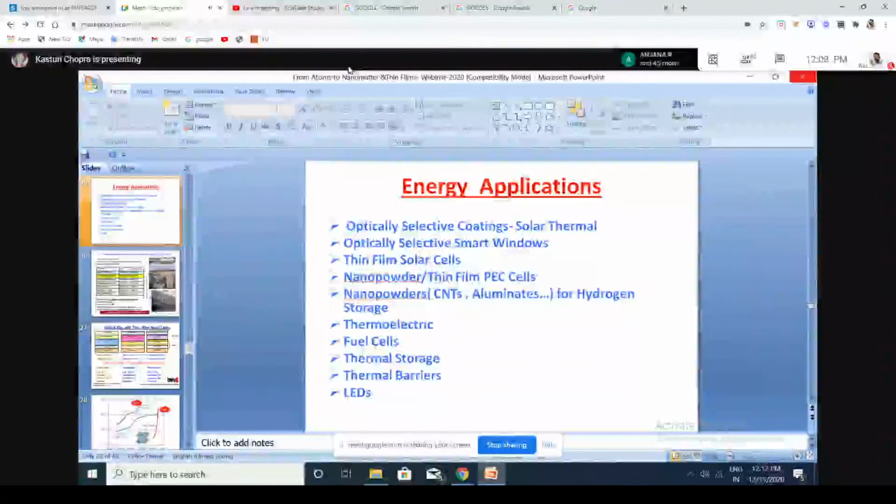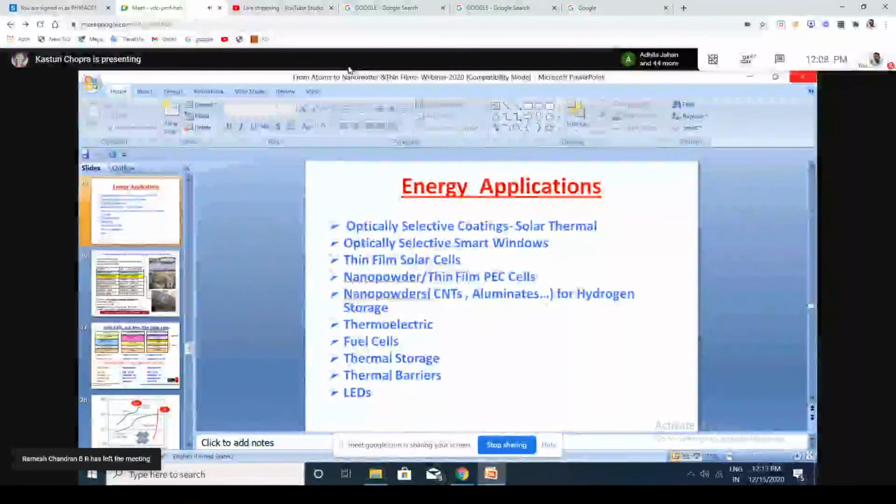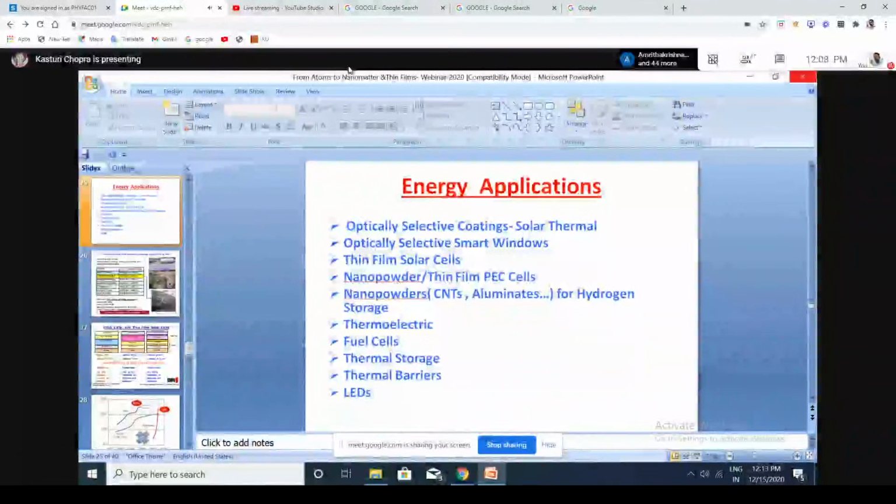And mind you, this is the principle we have to understand when we teach our first year physics here. We always teach good absorbers are good emitters. Okay, fine, but we don't say anything more than that, unfortunately. That is because the absorption process and the emission process can be separated out. They are in different wavelengths, for example. So that's exactly what thin film technology does. It gives a material which will absorb but not re-emit, for example. So the emissivity is very poor in infrared.